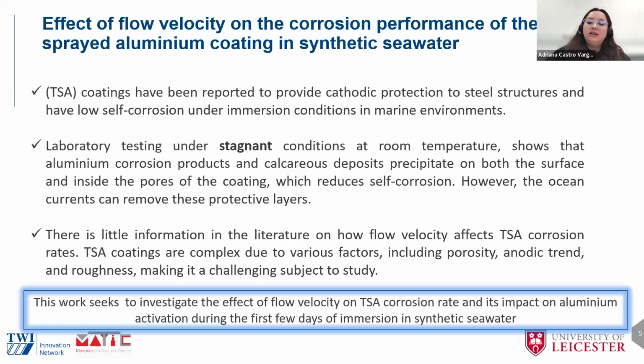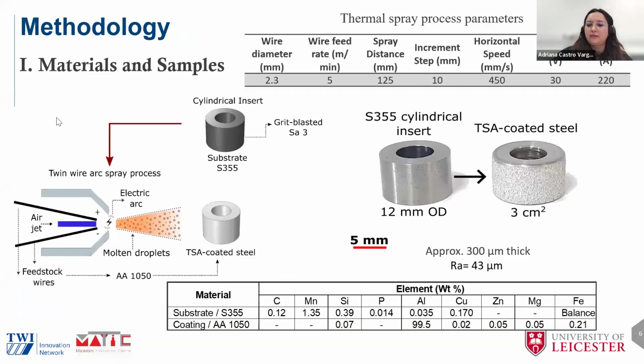So this study looks to evaluate basically the effect of flow velocity on TSA corrosion rate, and its impact on the aluminum activation during the first days of immersion in synthetic seawater. For that, we follow this methodology.